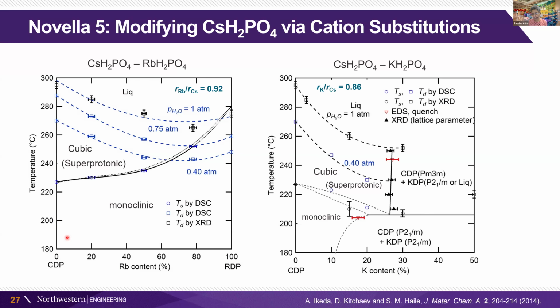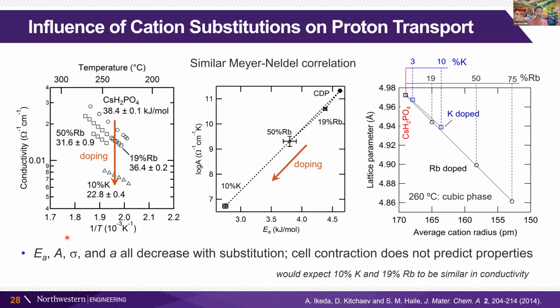Looking at the potassium system, the phase diagram is a little more complex because there's not complete solid solution between cesium dihydrogen phosphate and potassium dihydrogen phosphate. That makes sense because potassium is substantially smaller than cesium, but there is a window of the cubic phase. Again, the dehydration temperature decreases as we increase the potassium, which is unfortunate, but the superprotonic transition temperature does decline. So the window of operability is moving downwards and slightly narrowing. So the thermodynamic impact is not as negative in the case of the potassium as it is with rubidium. But we thought, okay, let's see what the influence is on the conductivity, because that's where we hope to gain some positive response. And unfortunately, the conductivity did decrease, opposite of what we just saw with the previous results.